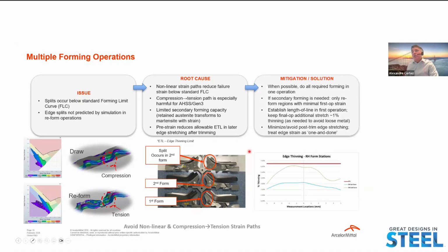As a mitigation solution, when possible, do all required forming in just one operation. If secondary forming is needed, only form with minimal first operation strain. Establish length of line in the first operation, and avoid post-trim edge stretching. Treat edge strain as one and done. Finally, in stamping, concerns about wrinkles, spring back, and lubrication.